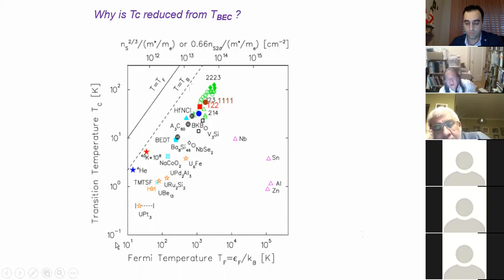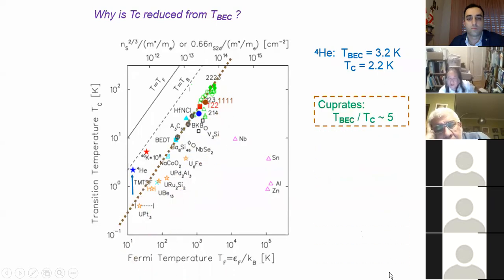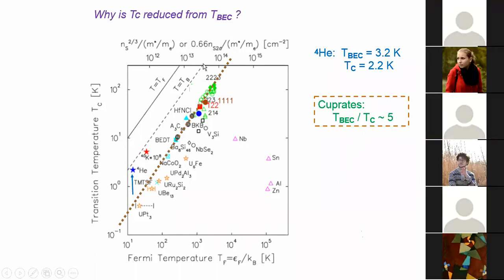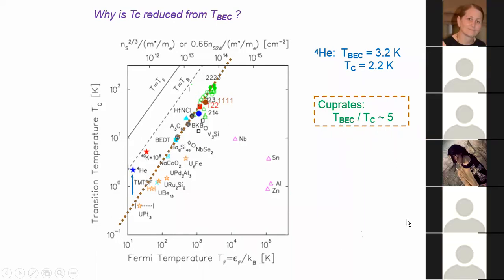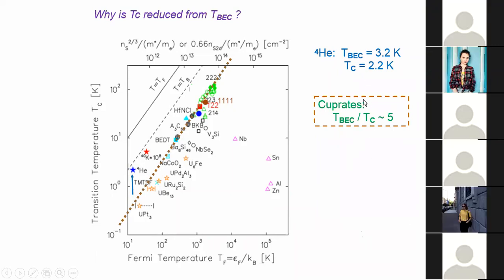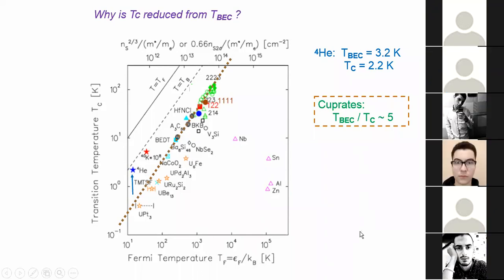And analogy can be made with this superfluid helium, because if you look at carefully, the superfluid helium, this idealized Bose gas condensation should have happened at 3.2 Kelvin, but the actual TC, the actual superfluid transition of the helium would happen only at 2.2 Kelvin. So this is about 50% reduced. And as I mentioned, in the cuprates, the actual TC is reduced from this idealized Bose gas line by a factor of 5. Okay, so although the magnitude is different, maybe similar phenomena.